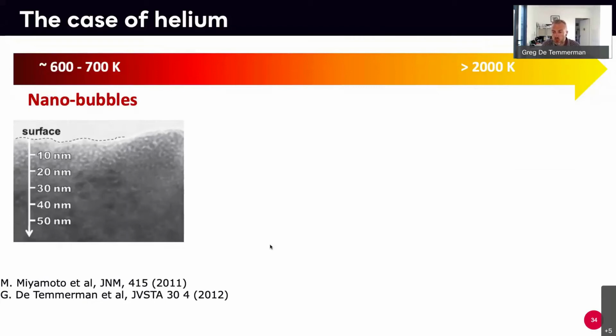You should not be able to put helium into tungsten, except that you have a very strong repulsion force between tungsten and helium. So when you put a helium atom in the lattice, helium will try to find a site and a defect to minimize the repulsion between itself and the tungsten atoms around. And when it does that, it's extremely strongly trapped inside the metal. So you have very high trapping energy because the helium atom is very stable where it is. It's basically stabilized by all the repulsion forces.